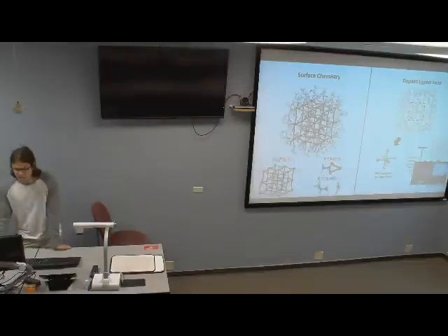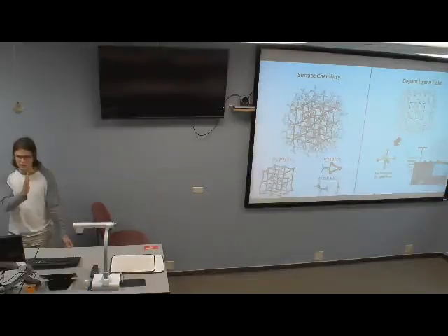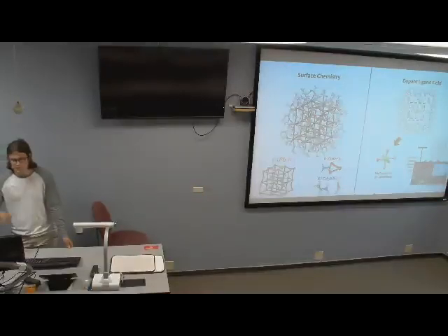And experimentally, they find that it's not the best surface passivation technique, because the ammoniums and the acids are basically aligned right next to each other, and so it makes it liable for that proton to transfer back and forth between them, and so it makes some of the ligands desorb and hurts the samples.